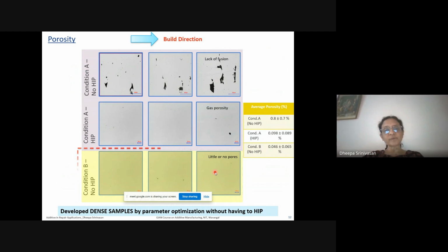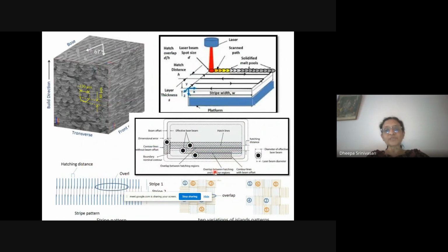So as we moved on, we looked at the parameter optimization. In some sense, as I showed you two slides earlier, what is the hatch spacing, which tells you the overlap in the layers, as you might have learned earlier this week. And we are also looking at what kind of scan strategy, is it a checker, is it chessboard, or is it a zigzag contour, and so on and so forth. So this whole thing was optimized so that the productivity is also met, and it's not a very slow process. At the same time, there is no compromise on the y equal to f of x, in this case density and simple room temperature mechanical properties.